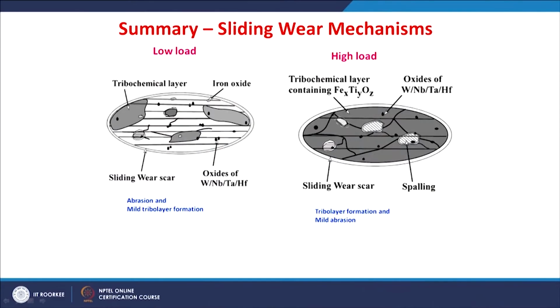So, overall, putting this as a summary of these sliding wear mechanisms: at lower loads there is a lot of abrasion and debris, and that leads to oxidation of this debris, and there is an onset of such tribo layers. But this layer becomes dense, covering the entire worn surface, and is rich with the iron titanium oxides. So, the layer is cracked and then removed. Mainly the wear occurs at higher loads by removal of such a layer rich with the iron titanium oxide, whereas at lower loads the wear is more dominantly by the abrasion, cracking or pull out of this material.